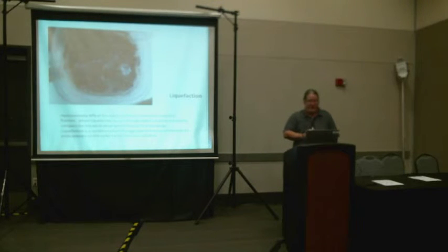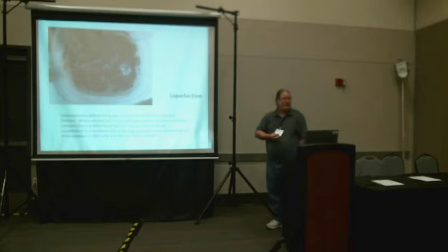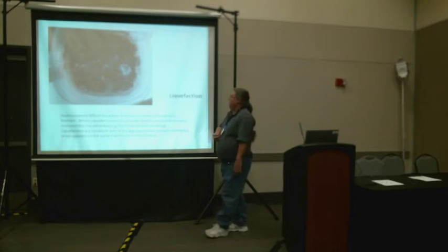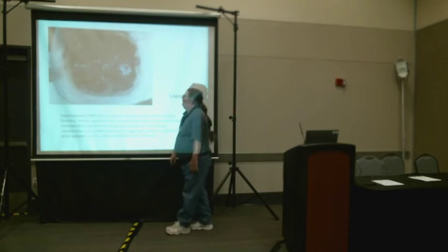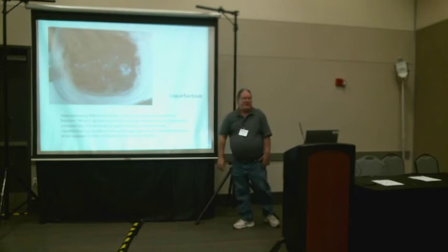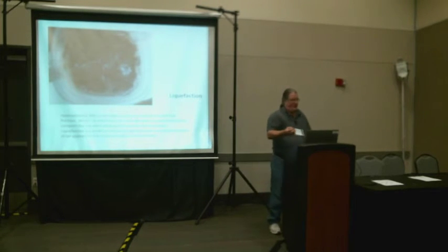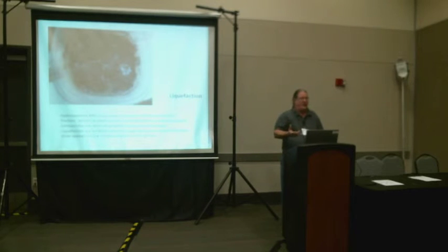I'm sorry for this picture, but we were talking about liquefaction, and I wanted to let you know what liquefaction looks like. And this is probably still on the vibrator, but you see this shine come to the surface. That's when the pores are full of water and there's no more room, and now you can put emulsion into this mixture, and the particles are not dry enough to break the emulsion.